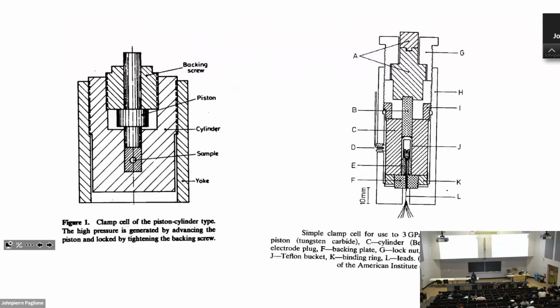That's a Bridgman cell. What I want to focus on more is the piston cylinder cell. So still in the clamp cell, instead of a Bridgman cell, you can just put a piston. So here is a sample space. Maybe this is a better picture. Here is your sample space. Typically, it's some Teflon capsule. I'm going to show you later. And then on one side you hold it from the bottom, and this is where your sample is, and your electrodes come out. This is the so-called feed-through. On the other side, you have a piston, which is typically tungsten carbide, and you squeeze, then you lock it.